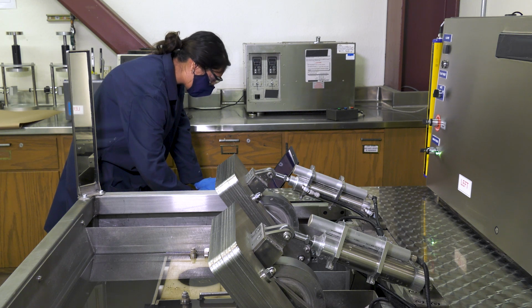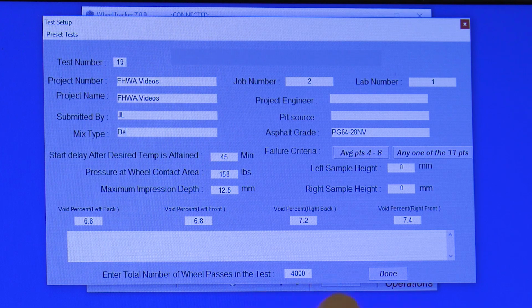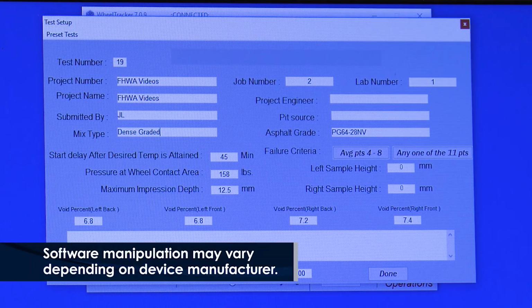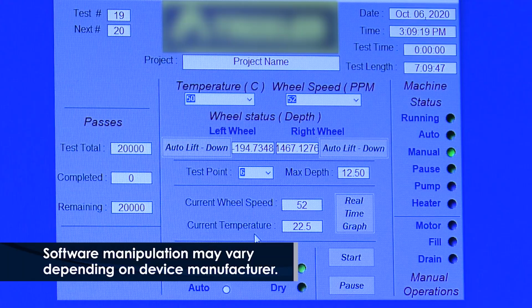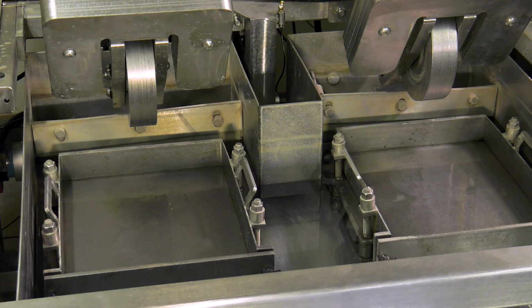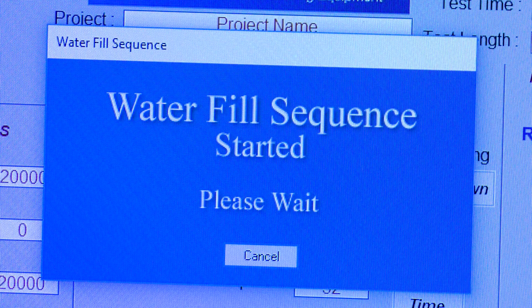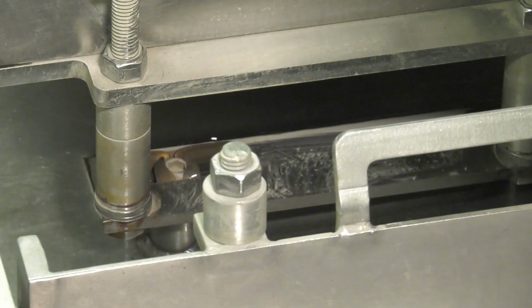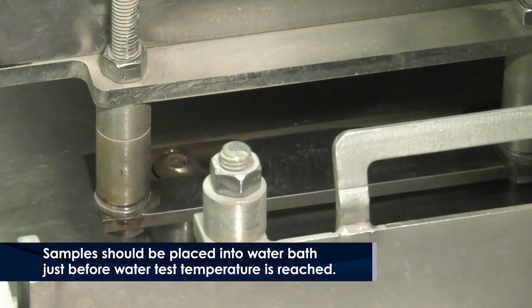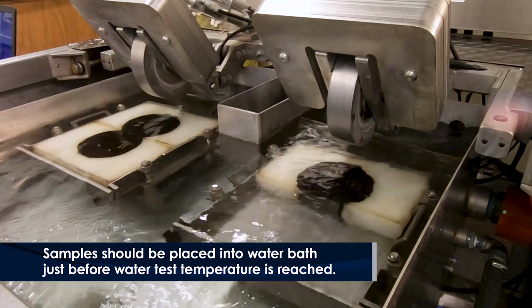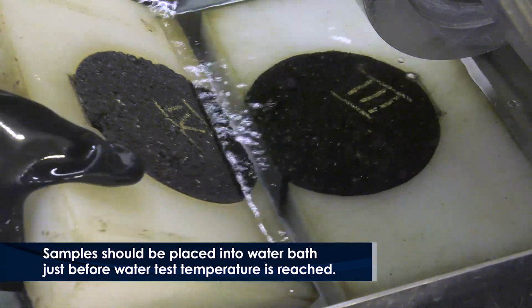Power on the testing device and all components and start the testing device software. Enter pertinent project information and testing configuration parameters. Select test temperature, allowable rut depth, and maximum number of passes based on applicable specifications. Fill the machine's water bath with water using the valves in the manual mode, or automatically if the machine can operate in automatic mode. Place the mounting trays with the test specimens into the Hamburg Wheel tracking device.